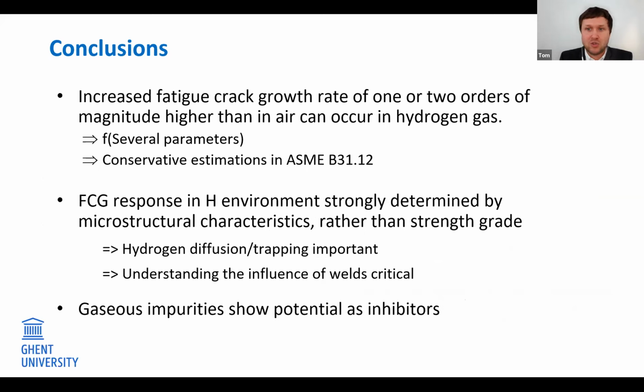A method to conservatively estimate the lifetime of a pipeline system is to use an upper bound of the fatigue crack growth rate data gathered from experiments, using different pipeline steel grades and loading conditions. This method is proposed in a new modification of the ASME B31.12 code concerning the fatigue lifetime of pipelines transporting gaseous hydrogen.